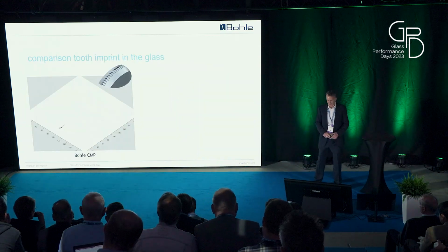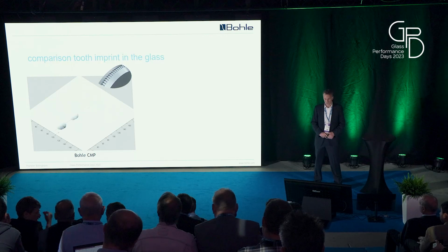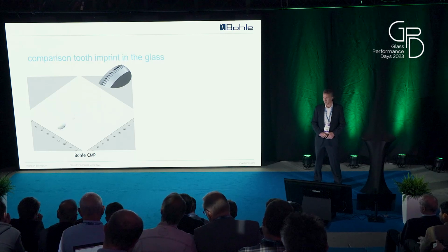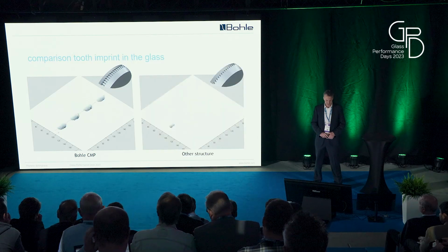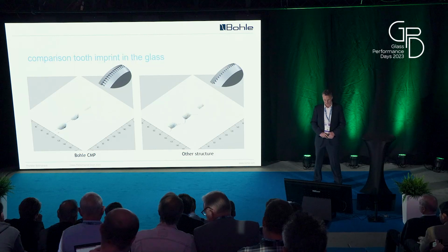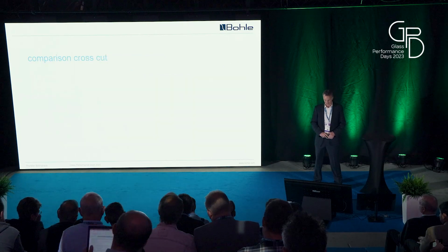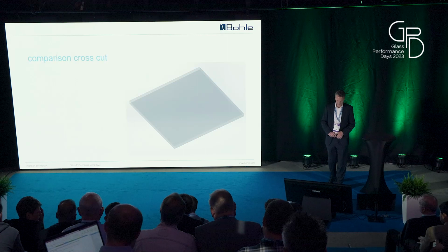What does this difference now make in the glass imprint? You can see here the linear effect that I was talking about before. You want that between two indentations, whereas if you don't have the recessed cutting edge that is continuous, then you get a side wing effect you don't want to have.